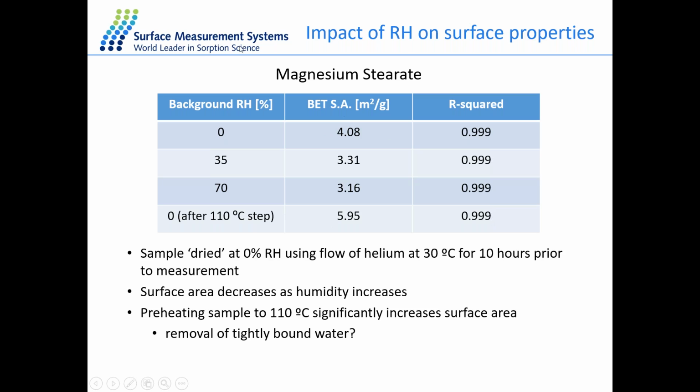If we measure this kind of sample directly with the nitrogen sorption technique at liquid nitrogen temperature, the hydration water will be lost during the measurement, and this is probably the value we will get from the volumetric method. But it's not the original sample of interest anymore, and it's not the real surface area during the processing or performance. In the case of the vapor sorption technique, we can detect this kind of difference before and after the hydration water loss.